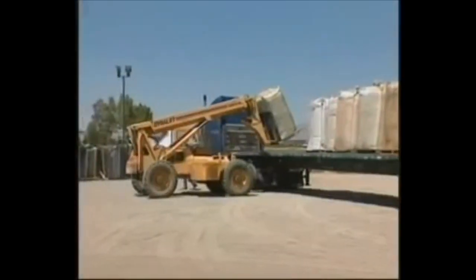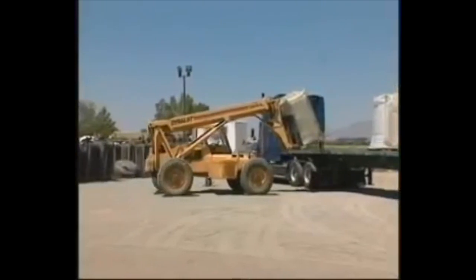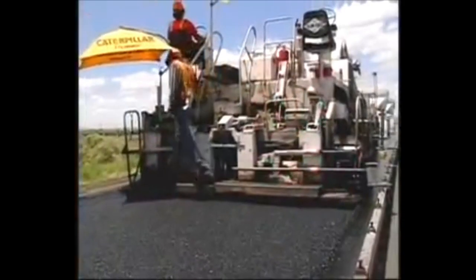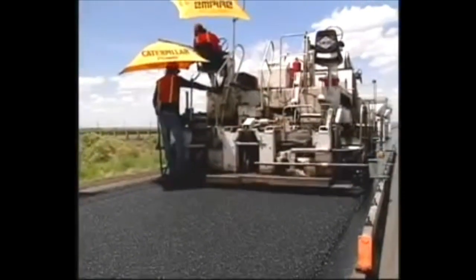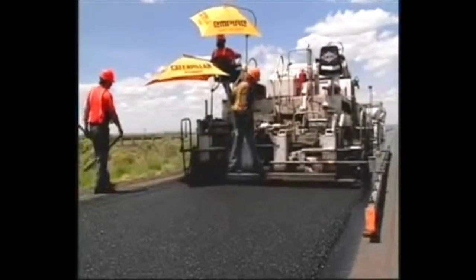There, the crumb rubber is blended with asphalt cement under a time and temperature formula inside a large tank. It takes about an hour for the rubber to react with the asphalt to form an asphalt rubber binder. To qualify, according to the established ASTM standard, the blend must contain at least 15% rubber by weight, and the rubber must react with the hot asphalt enough to cause the rubber particles to swell. Standard practice of 20% plus or minus 2 of rubber produces optimum physical properties. The binder is tested in the field to meet specifications.